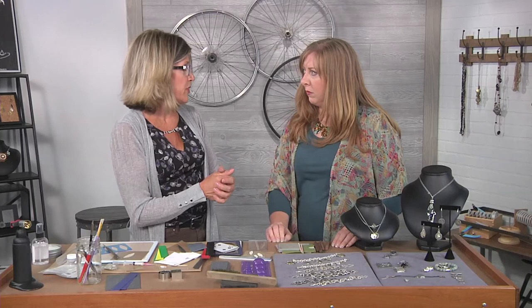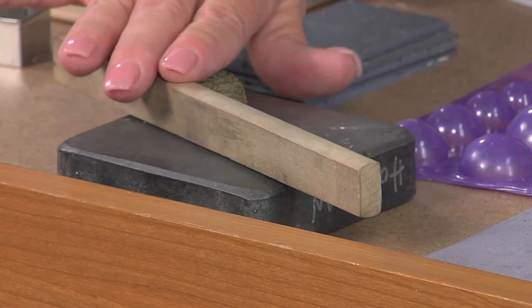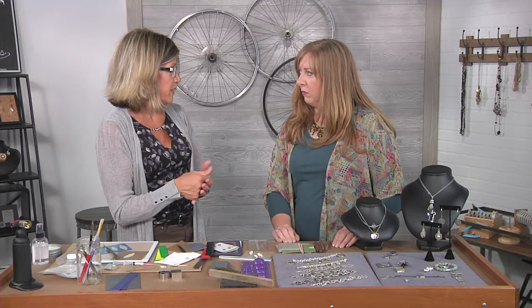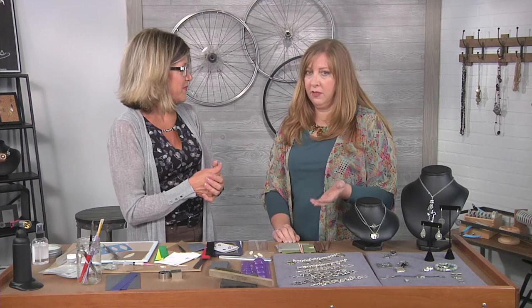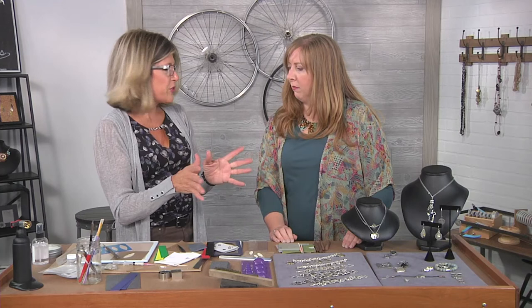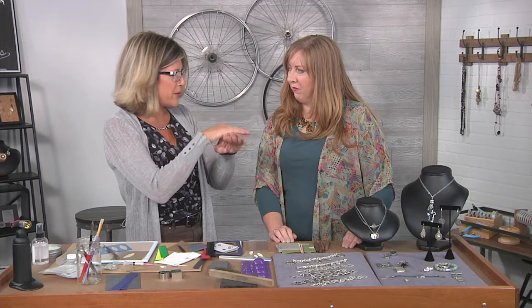After firing, you brush it — and we should mention it comes out of the kiln looking white, which can be scary, but it will become silver once you take care of it. That white appearance is just the surface topography not reflecting light; there's no coating involved. You can burnish it with a brass brush or a burnisher, or tumble it with stainless steel shot. Burnishing knocks down the bumpy surface molecules so the topography becomes smooth and reflects light, giving you that shiny silver finish.